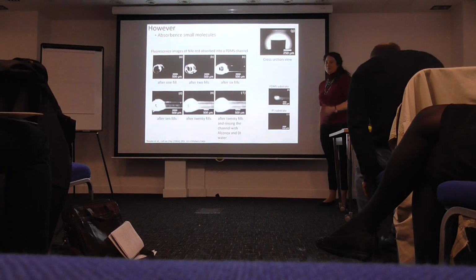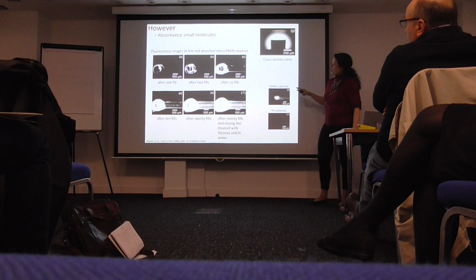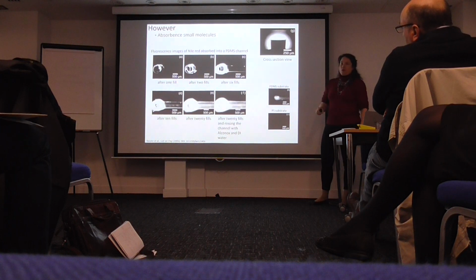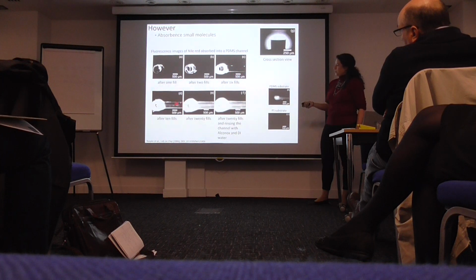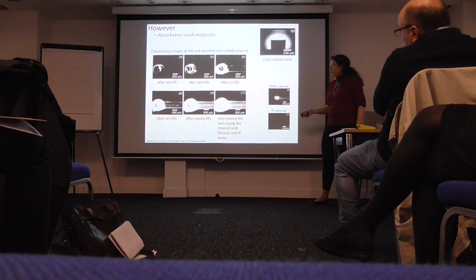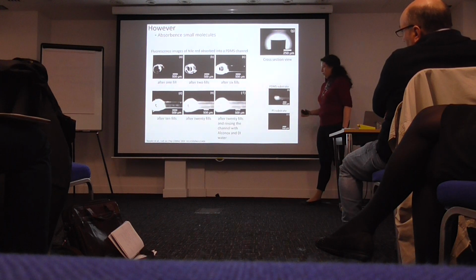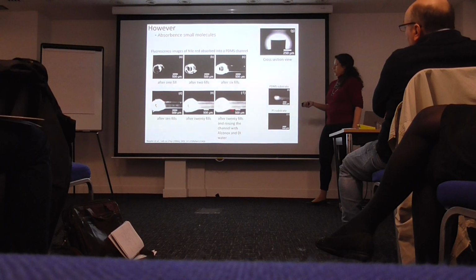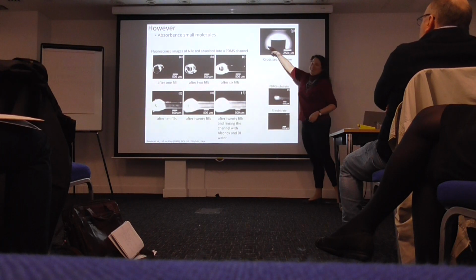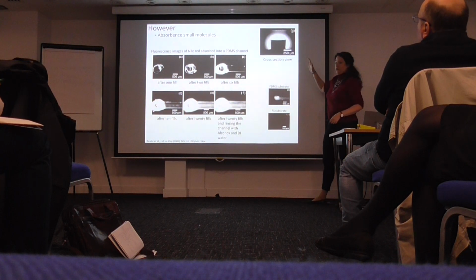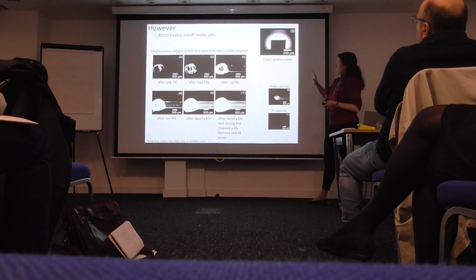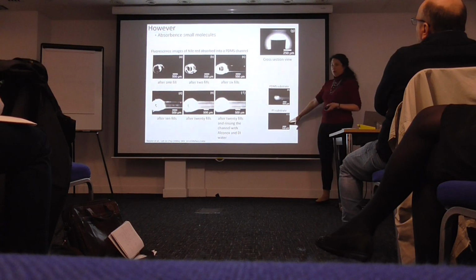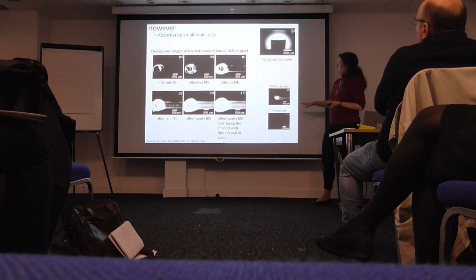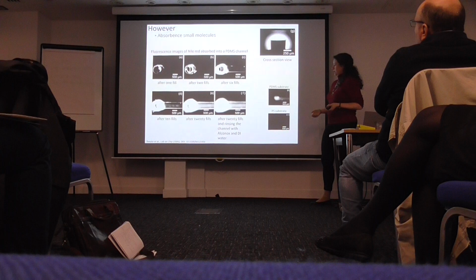I do know that some of you are already aware of the challenges, but just to make sure, PDMS absorbs small molecules, and it absorbs a lot. If you're looking at images of Nile red, after 6 fills you clearly start seeing the sides of the channels. After 10, 20 fills, even if you wash after with ethanol and any alcohol or solvents, it's all in the channels. And if you do a cross section, you can see that it is inside of the PDMS. It's not just on the walls. It literally absorbs it. And it is a problem of the PDMS because if you do the same thing on polystyrene, you don't get that absorption. So if you're dealing with any fluorescence, then it's quite problematic.